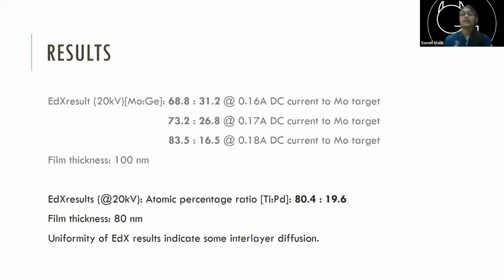And for electron beam evaporation, since I was doing alternate depositions, it took me about 4 hours of continuous deposition, because there is waiting time between the electron beam evaporation and the thermal evaporation. You need to wait for the system to cool down before using it again. So roughly 4 hours to deposit 4 layers of titanium and palladium each. And then you need to switch off your system, and it takes another hour waiting for the turbo to come down to 0 to get your chips out of the chamber. So time consuming, yes.